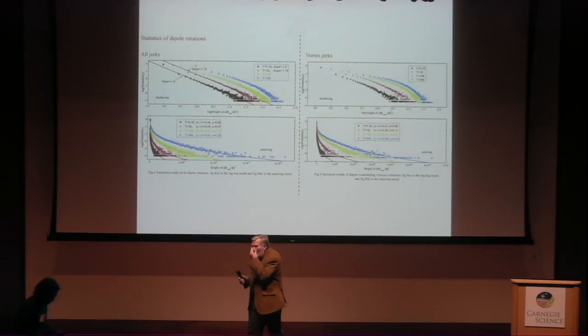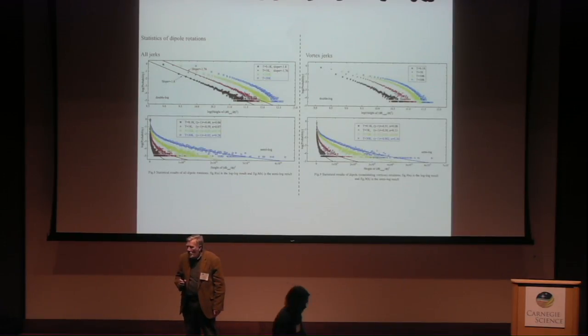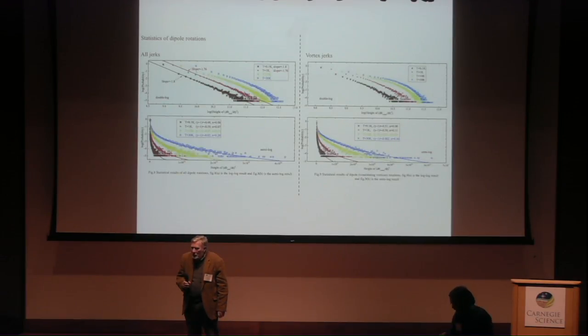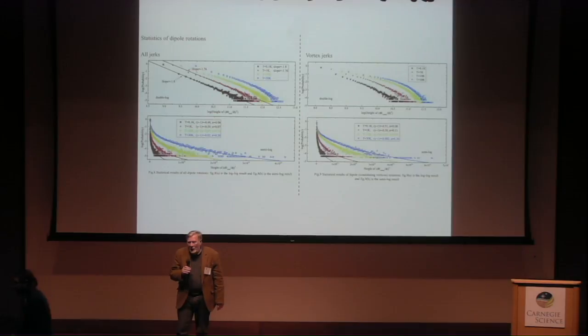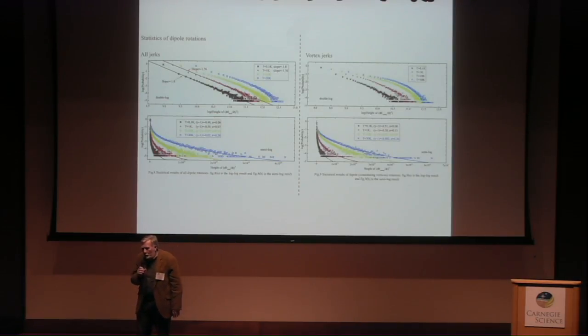Eckhart, for just other reasons which you know about, I would like to know, if you take tungsten bronzes and you have the domain walls, you make them superconducting. Yes. But what is the origin of the superconductivity in the walls? Well, we don't know for certain what's in the wall, but if we make the entire material superconducting, which we can also do, then it's quite clear it's real space pairing. It's not BCS, and it's bipolaronic prefabricated bosons, which then condensate. So it's a Bose condensation.